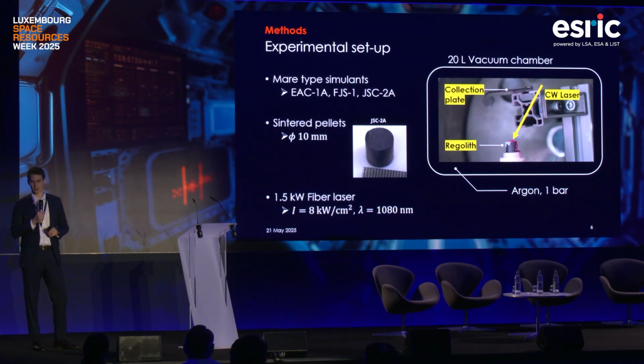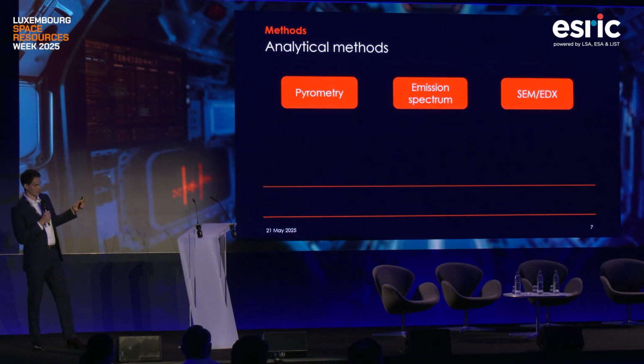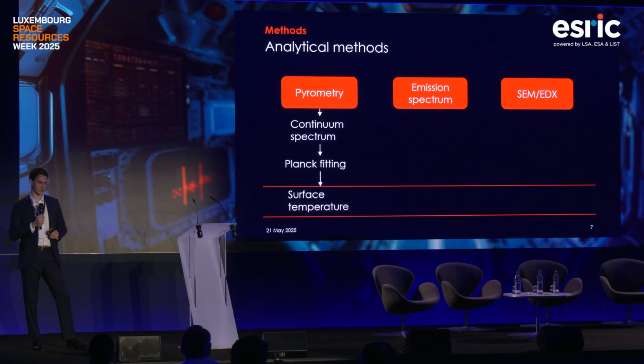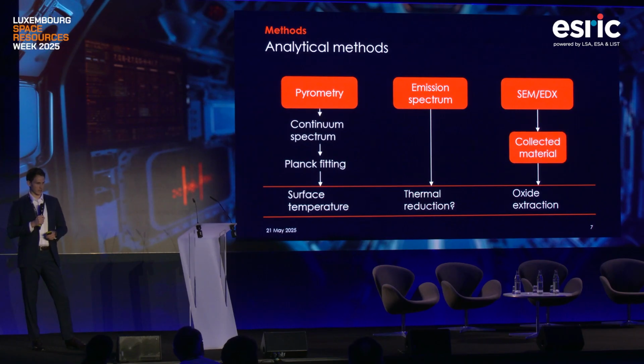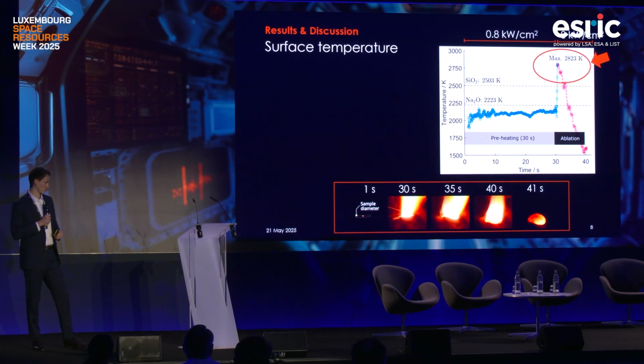The laser is a 1.5 kilowatt fiber laser with a wavelength of 1080 nanometer, and at a spot size of 5 millimeter diameter, we can create an intensity of 8 kilowatt per square centimeter. Then we measured the temperature using a pyrometer of the surface and a spectrometer to see what kind of species we produce. So the analytical methods would be pyrometry for surface temperature measurement, emission spectrum to see what kind of species we have, and whether we even have thermal reduction present, and most importantly, SEM EDX of the collected material to see what we actually extract at the chosen conditions.